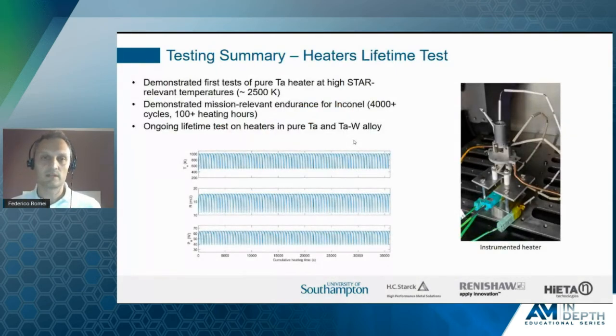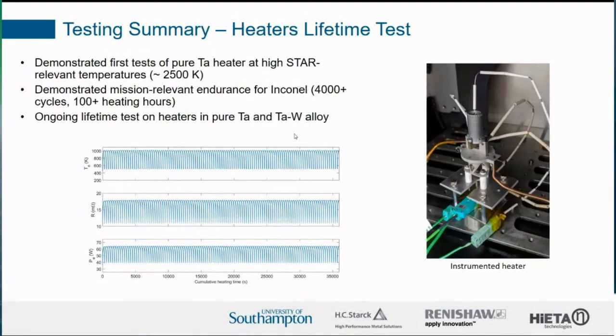Then, moving from the material testing, we performed, and we are still performing, a number of lifetime tests for the heaters. So on the right, you see a heater instrumented with thermocouples and placed into the thermal vacuum chamber of the University of Southampton. And what we have done basically is to cycle the heater from ambient temperature, so 20 degrees Celsius roughly, in vacuum to the maximum operating temperature. So we have done this both for Inconel and we are doing it for refractory. And the goal is to demonstrate that this heater can meet the requirements for a typical mission.